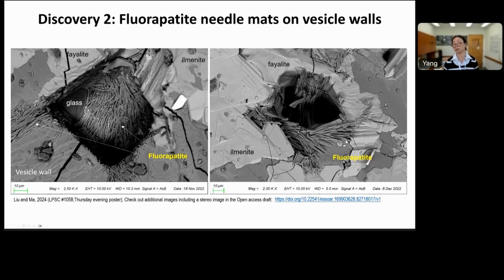In both cases, we do not see abundant silicate minerals associated with fluoroapatite needles. There are small amounts of other minerals, but not silicate minerals. And so far, we observed 2 cases on vesicle walls for this sample. We studied like 4 different chips, several different vesicle walls.